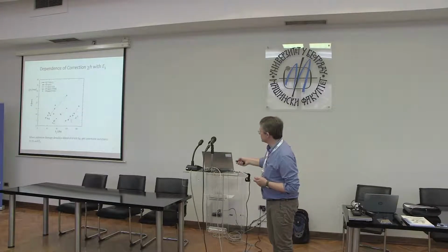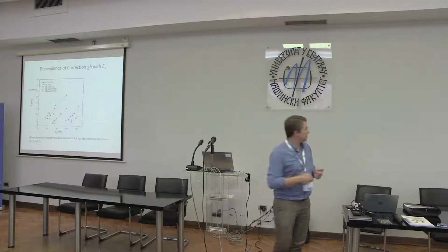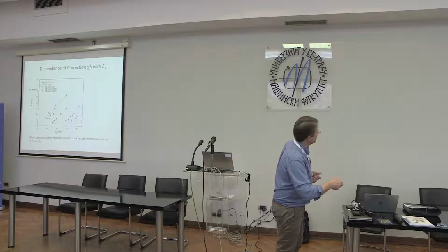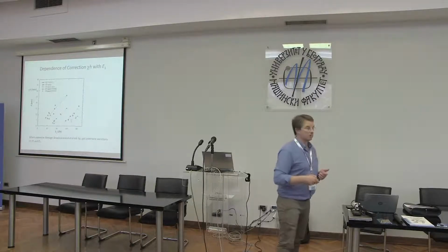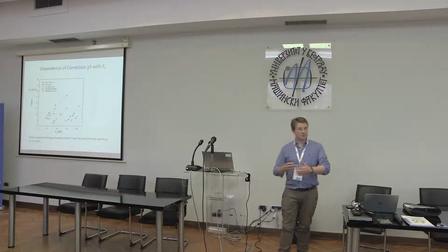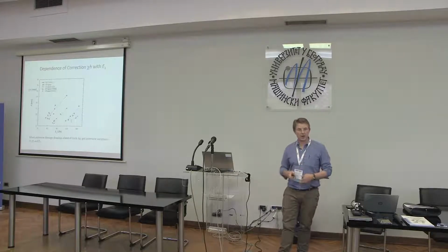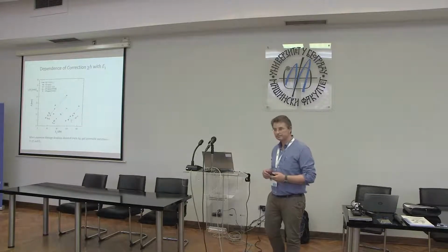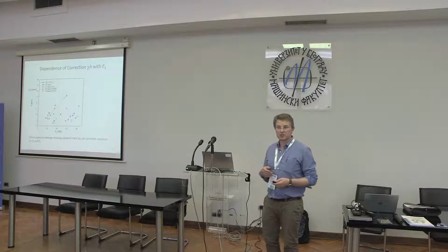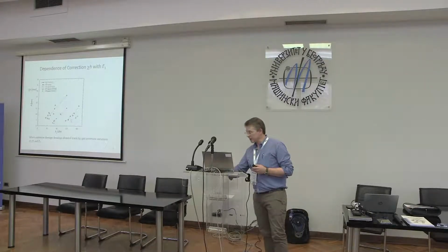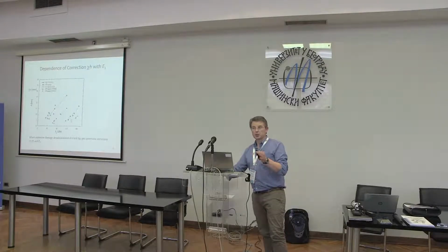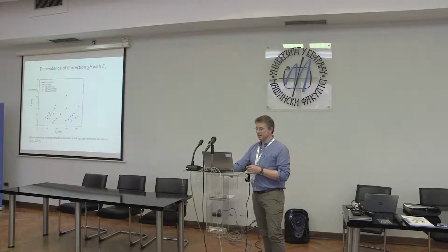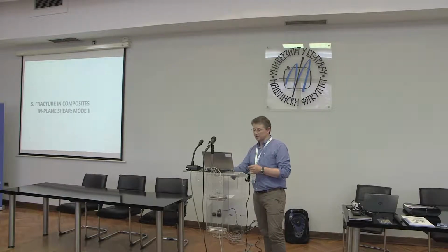So, for example, these data here were for some glass fibre reinforced PMMA. That was one batch of specimens. And across that one batch of specimens, we had this large systematic variation in the fracture parameters. So obviously cause for concern. One has to inspect these data carefully when they stop behaving in the classic linear elastic manner that we anticipate.